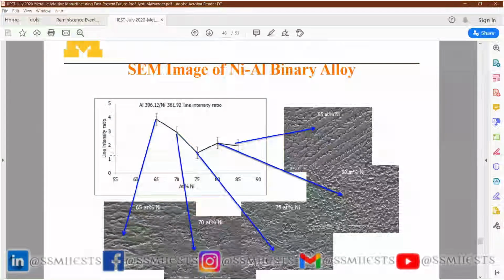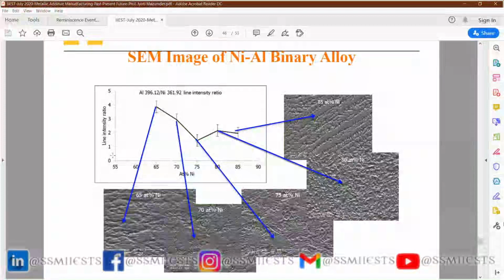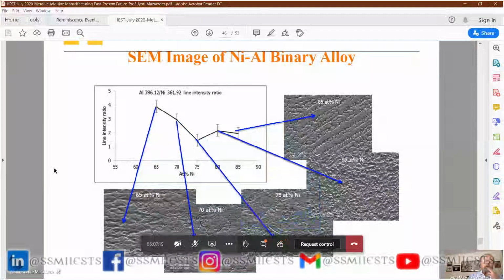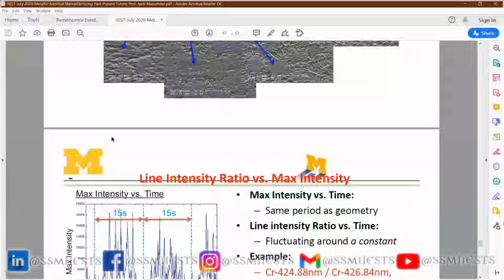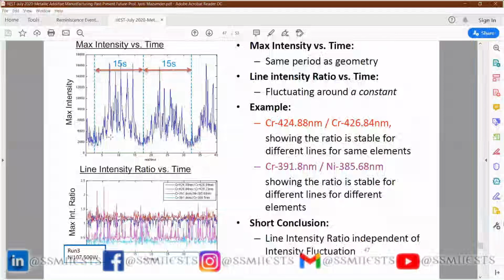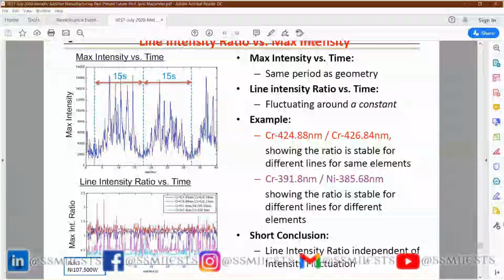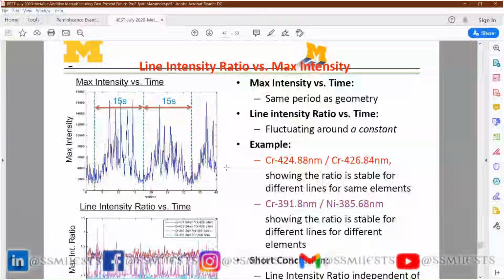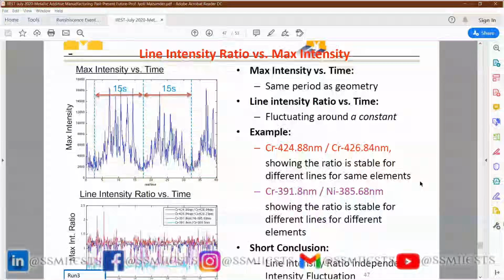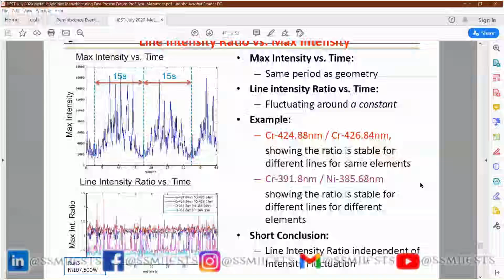Now, one of the questions when we started presenting this at TMS, the Materials Conference, some of my colleagues asked, "Oh, the plasma is always fluctuating. How do I know I'm getting the right signal?" What we wanted to show is that if you take the ratio, then it's pretty much stable. So you take the line intensity ratio versus time, and I'll give you an example like chromium. It has emission at both 424.88 nanometer and 426.84 nanometer. So the ratio is stable. Using that, we found that line intensity ratio is independent of intensity fluctuation. So by taking the ratio, we can cancel out the process fluctuation, you can avoid that.